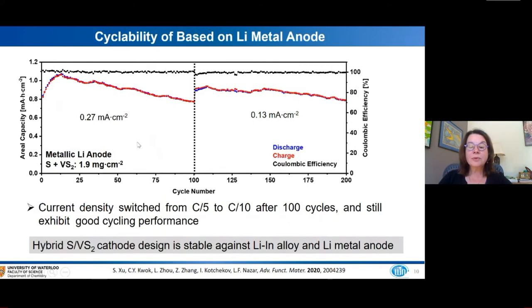We've also investigated the rate performance of the system, where we switched from C over 5 to C over 10. So this is the C over 5 data, the C over 10 data. We have the current density, and we've cycled the cell for about 200 cycles over this period of time. It still exhibits very good cycling performance. And this is the total loading in the system.